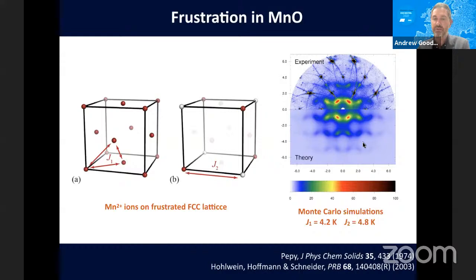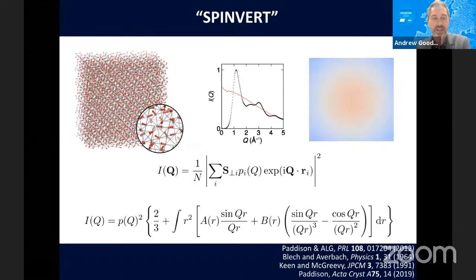And once you have that, you can work out what the scattering looks like. Here's a comparison from nearly 20 years ago between a Monte Carlo simulation and a cut through that three-dimensional diffuse scattering that I showed you before. That's really quite nice. But of course, this is starting from the theory and comparing with experiment. Very often as experimentalists, we want to take our experiment and derive, say, the structure from that. You can do that in a number of different ways. Here's one that we often use within the group. This is based on the reverse Monte Carlo approach developed by Robert McGreevy, who'll be known to all.